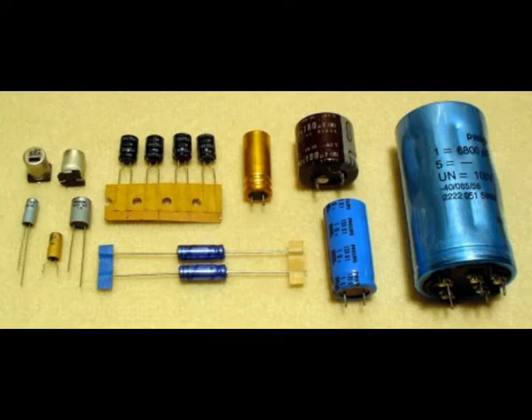At a reverse voltage lower than -1.5 volts at room temperature, the cathode aluminum foil begins to build up an oxide layer corresponding to the applied voltage. This is aligned with generating hydrogen gas with increasing pressure. At the same time, the oxide layer on the anode foil begins dissolution of the oxide, which weakens the voltage proof. It is now a question of the outside circuit whether the increasing gas pressure from oxidation leads to bursting of the case, or the weakened anode oxide leads to a breakdown with a short circuit.